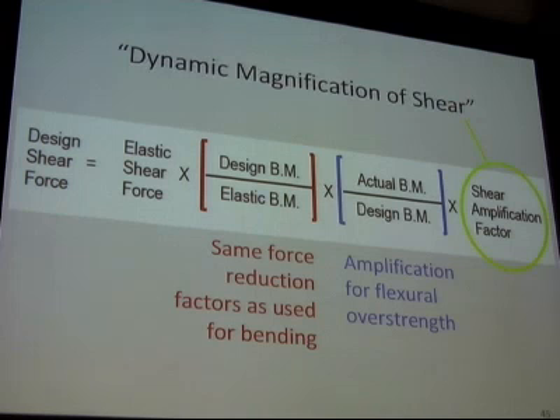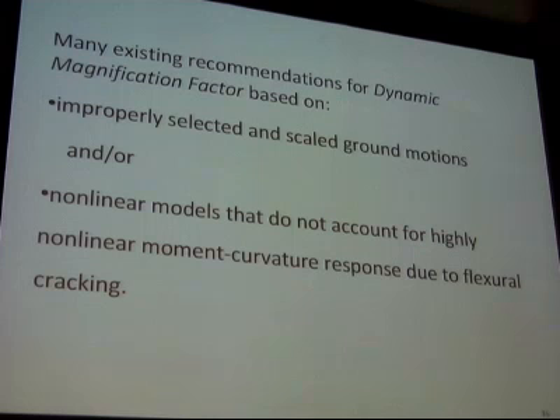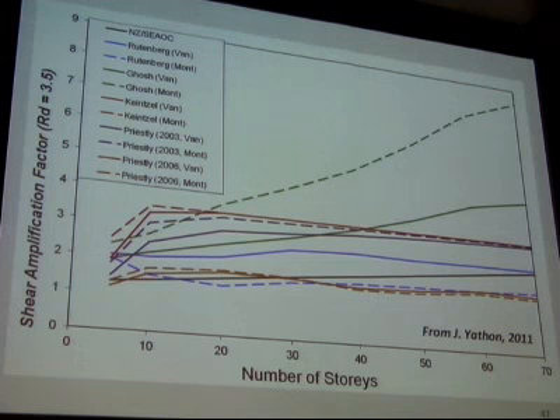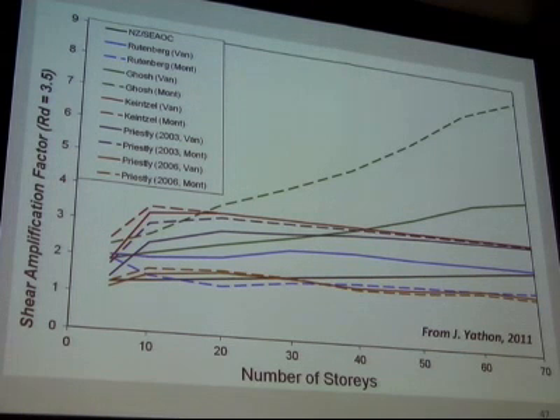But there's another factor, which is an amplification factor to account for the fact that the higher mode shears aren't linked to the flexural capacity. And a lot of people have done work on this, including, again, Patrick and Robert Tremblay. I don't know if he's here yet, but Robert's done work on this. And many people have different solutions. My own conclusion is that a lot of the suggested amplification factors are too large because people have used a bad model and have used the wrong selection and scaling of ground motion.